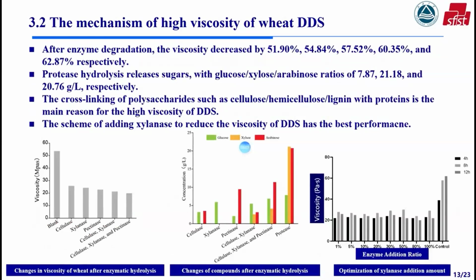After degradation of wheat DDS with proteinase, the highest amounts of glucose, xylose, and arabinose are released. Among these, the concentration of arabinose and xylose both exceeded 20 grams per liter, while the glucose concentration is nearly 10 grams per liter. Enzymatic degradation experiments indicate that the intercross linking of macromolecular compounds is a primary cause of the high viscosity of DDS.